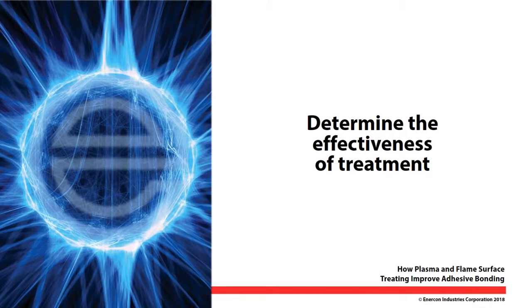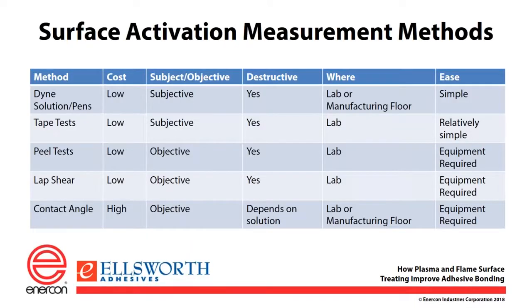How do we determine the effectiveness of the treatment? Here are some common methods: Dyne pens, tape test, peel test, lap shear, and contact angle. And this goes through the cost of these individual methods, if it's objective or subjective, destructive, where it happens, and the ease of use. Most often we're using Dyne or contact angle to measure the surface energy.